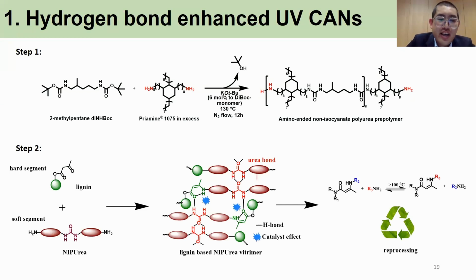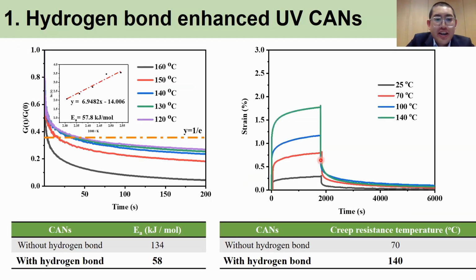First, let's talk about the hydrogen bond enhanced system. We prepare the amino-ended non-isocyanate polyurea prepolymer, then cross-link with the modified lignin to prepare the networks, and the urea bonds in the system can provide rich hydrogen bonding. And this hydrogen bonding helps to increase the properties of the material. The hydrogen bonds can catalyze the bond exchange of the material, reducing the activation energy. Additionally, the hydrogen bond can significantly improve the anti-creep performance of the material.